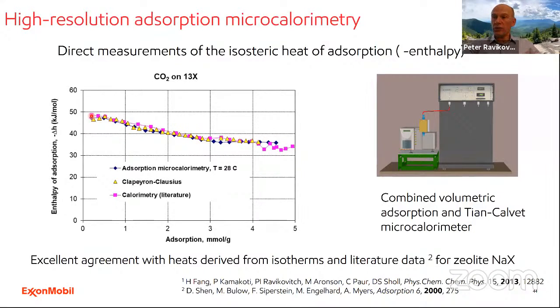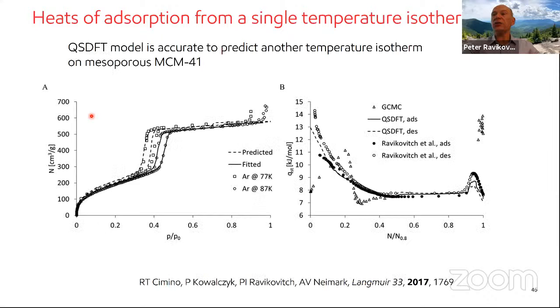In certain situations, you can use one temperature to calculate heat of adsorption, but at the condition that you have a perfect adsorption model. So this is an example of a quench solid DFT, classical DFT model, which predicts rather well adsorption on mesoporous materials such as MCM41. In this case, you can measure one isotherm, and you can fit this one isotherm using the pore size distribution, using the kernel of theoretical adsorption isotherms.